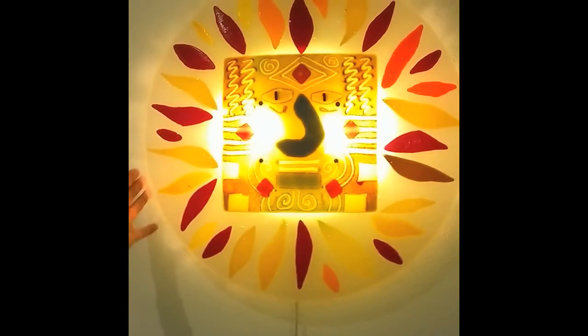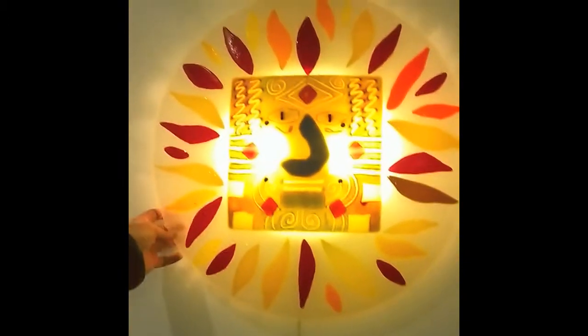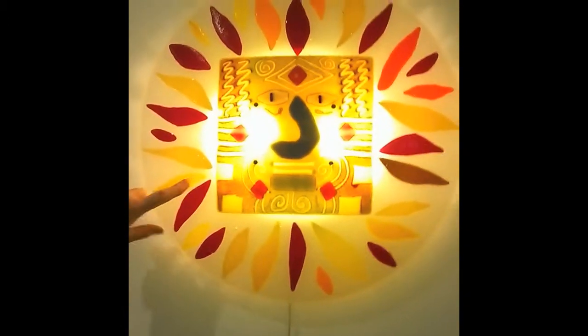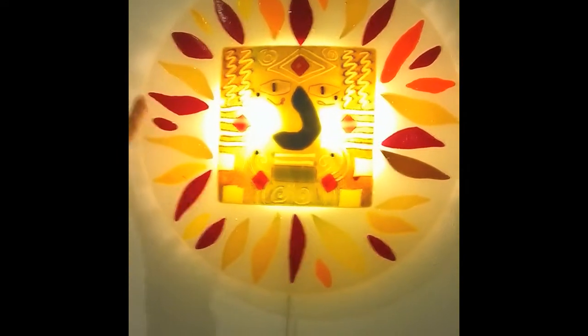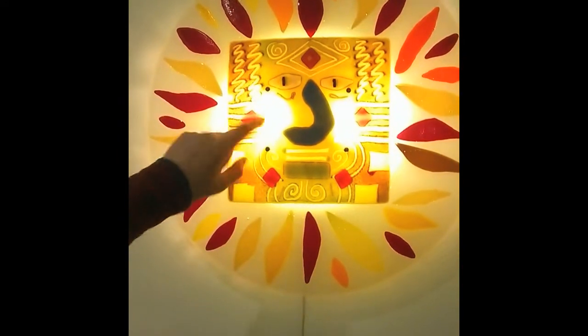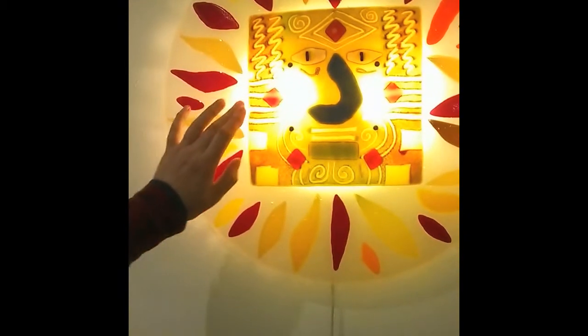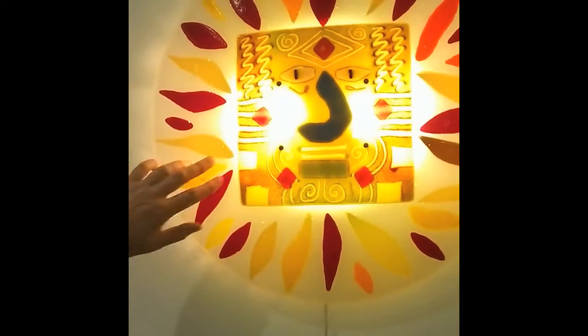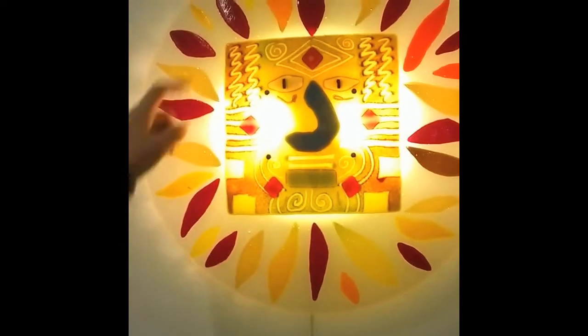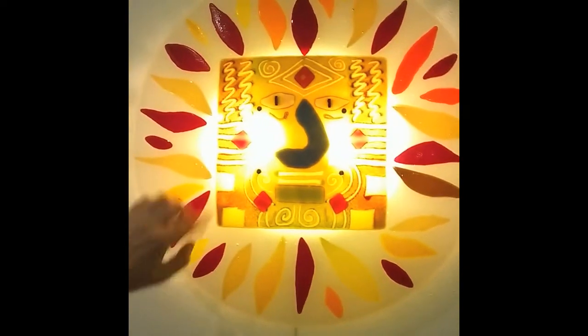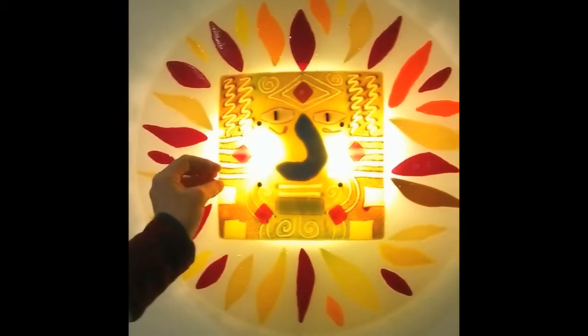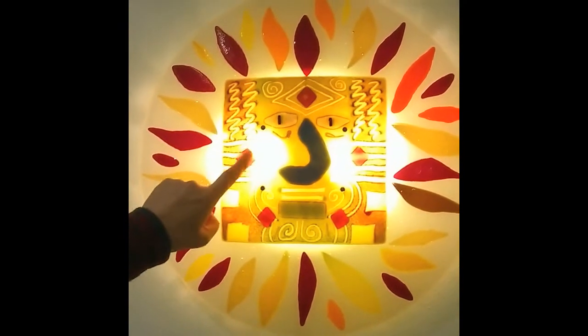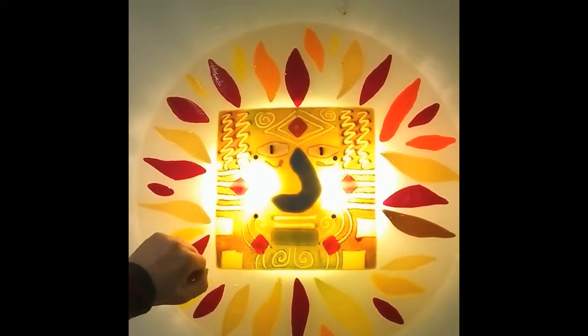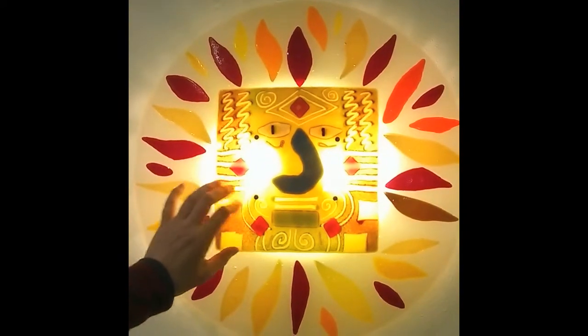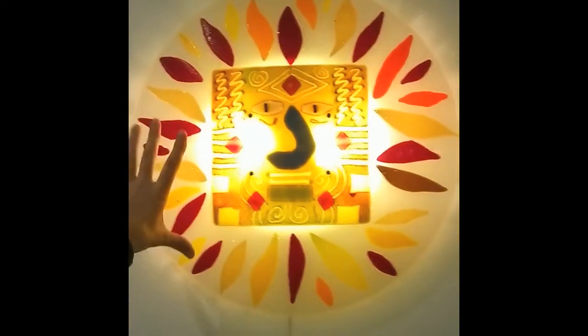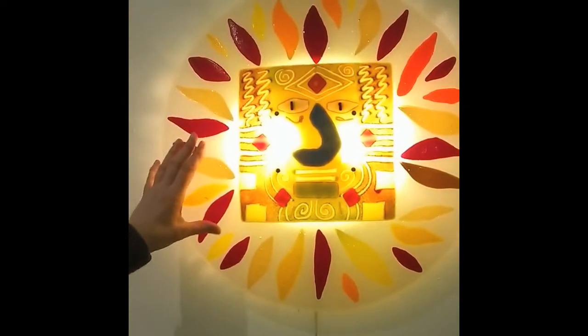Yes. First, I start with a big disc of transparent glass. Then I cut all these different colors from a bigger sheet. And this is a very special technique. You see these colored pieces, are they again pieces of glass, or is it glass powder? No, this is glass. These are pieces of glass. Right. And this is a big piece of yellow glass. And I put different glass powders on. Okay. And I have to melt this one time in the oven at about 820 degrees. First, I melt everything together.